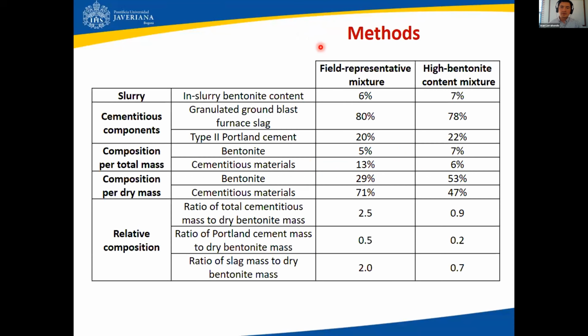So what originally Norte and Jeff did back in the lab was preparing two main mixtures of slag-CB, and then they applied mineralogical methods to try to study the evolution of those mixtures over time. What you see here on this left column is the mixtures that are representative of field construction in typical slag-CB cutoff projects. What you see on the right-hand side, though, is a second mixture that was prepared for validation, or sort of confirmation of the previous one, and it's a spiked mixture. It's a high bentonite content mixture, and you can see the proportions over here.